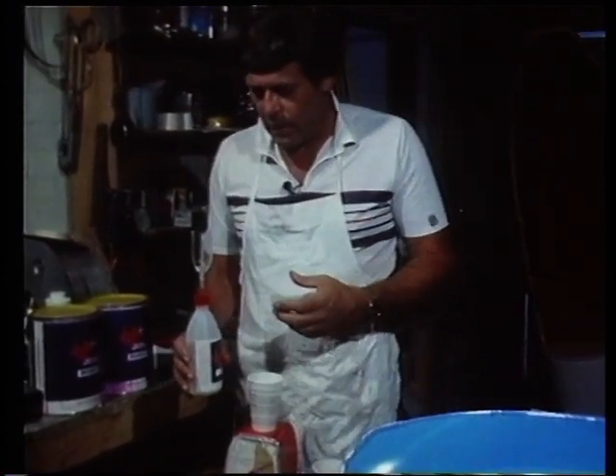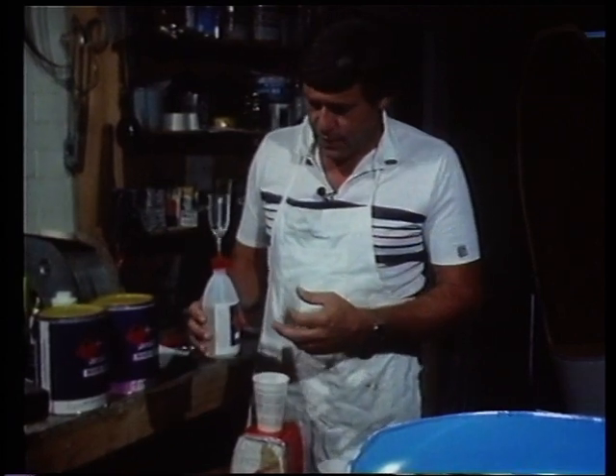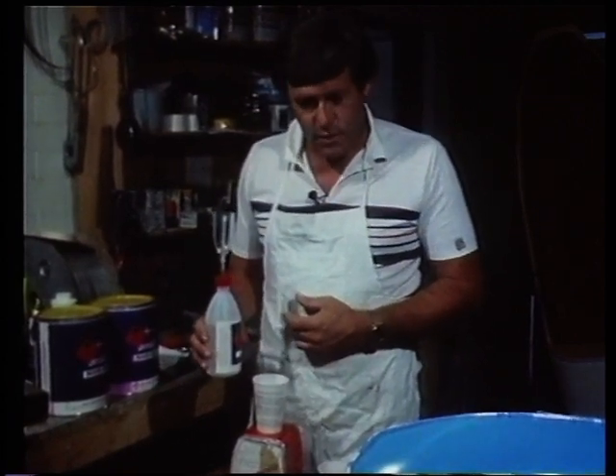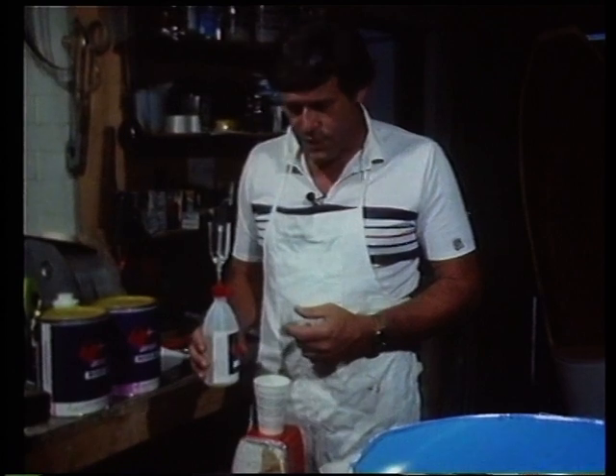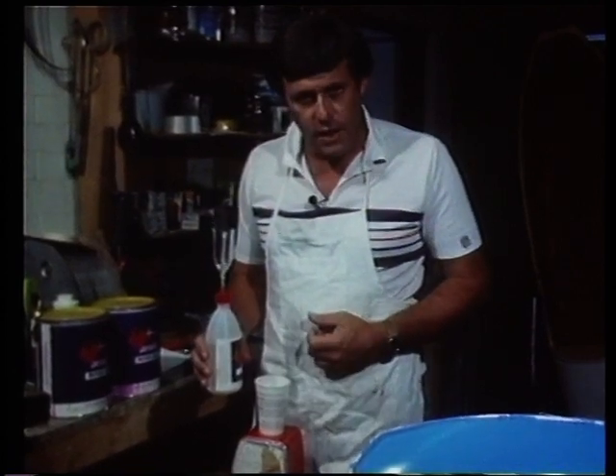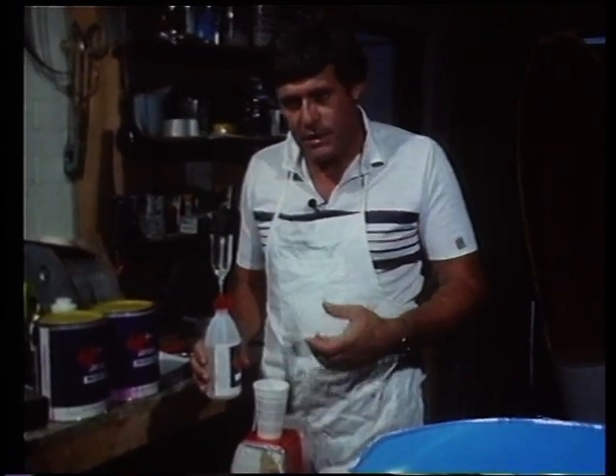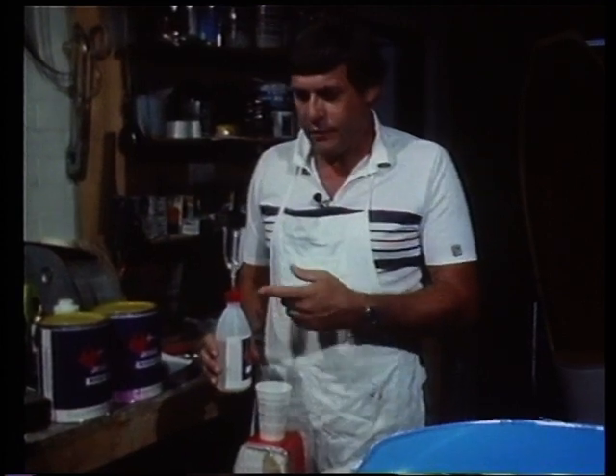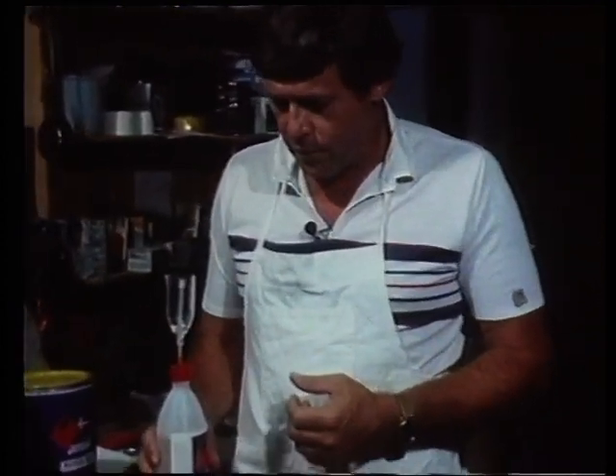Now before we mix it, a few words about catalyst. It's methyl ethyl ketone peroxide. It's an organic peroxide, which means that it has drastic effects if it touches tissue, particularly eye tissue. Now if you get that in your eye in its undiluted form, it will cause damage which becomes cumulative. In fact, I've known people who've had catalyst in their eyes when they were 19 or 20, irrigated it out fairly quickly, and had no idea that they had continuing troubles until they were 35 or 40 when eye problems came along.